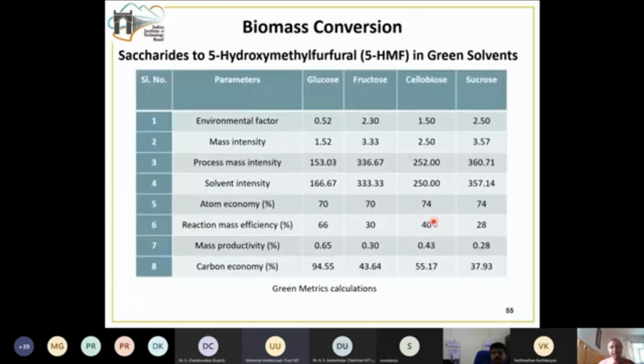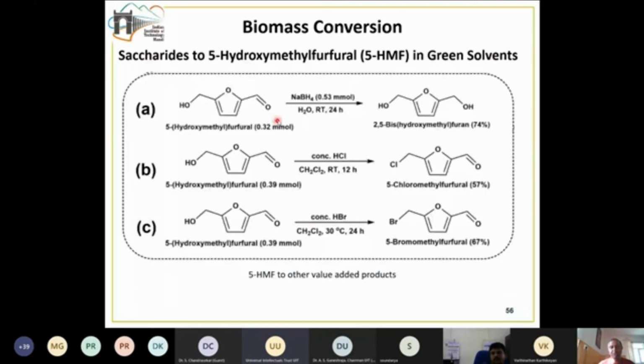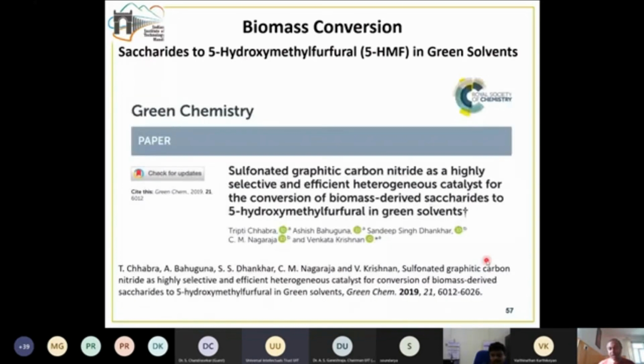Then we did a detailed green metrics calculation wherein we determined the environmental factor, mass intensity, process mass intensity, solvent intensity, atom economy, reaction mass efficiency, mass productivity, and carbon economy for various different substrates ranging from glucose, fructose, cellobiose, and sucrose. And the obtained 5-HMF was further converted to other valuable products using normal procedures in relatively good yields. And this work was done by my current PhD scholar, Ms. Trapti Chabra, and this was also published in the journal Green Chemistry in 2019.